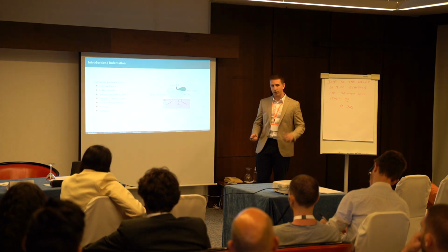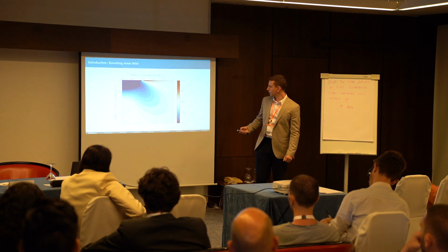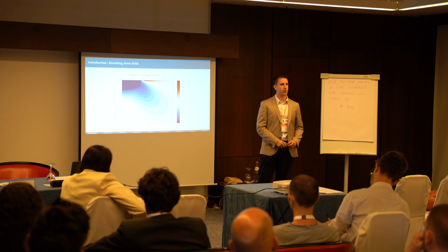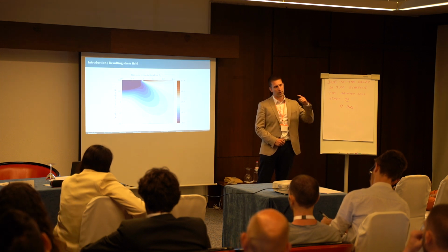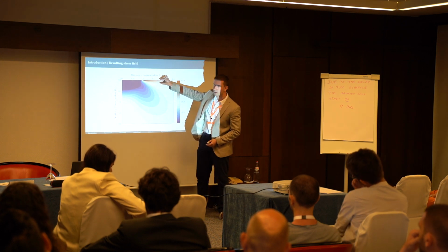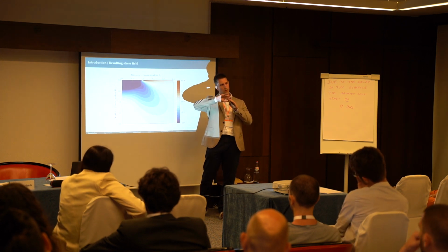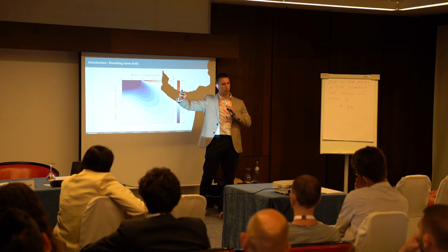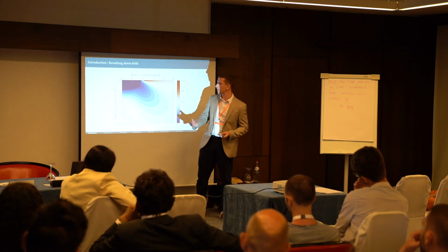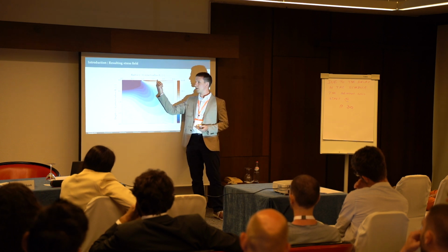And when you push it, you induce stresses, and the component in the radial direction is tensile only in a certain region below the surface, and it's always outside the contact radius with the ball. So the crack, if it should fulfill the coupled criterion, should probably be initiating in this region.